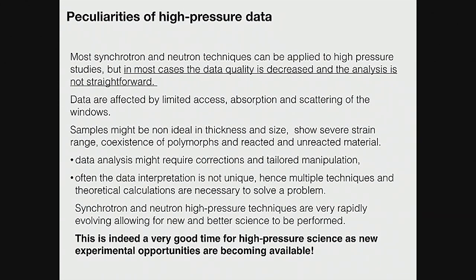So you have access to this sample through small windows. These windows will also interact with your X-rays or neutrons, so they will give their scattering contribution. Your sample, you probably heard from the XAFS talk that your sample should really have a certain thickness, it should be uniform, it should not have holes and all of these. But that's very difficult to obtain at high pressure. And you have a range of grain sizes, and it changes over time. So the problem is that, first of all, you have to be aware of it when you design your experiment, when you collect your data, and also your data analysis might not go through smoothly.